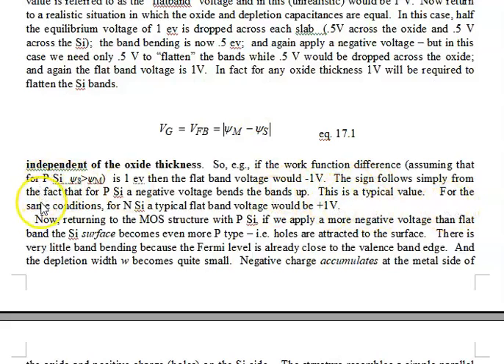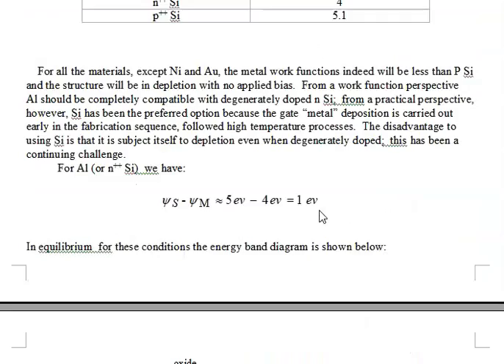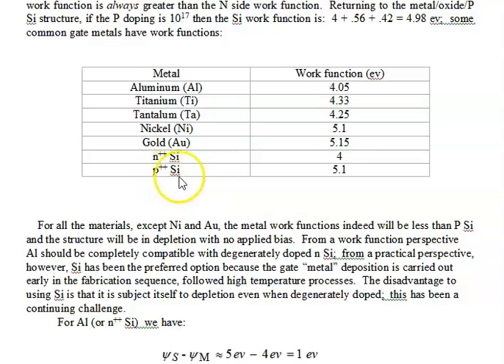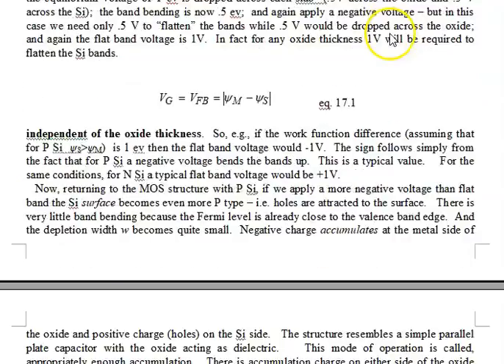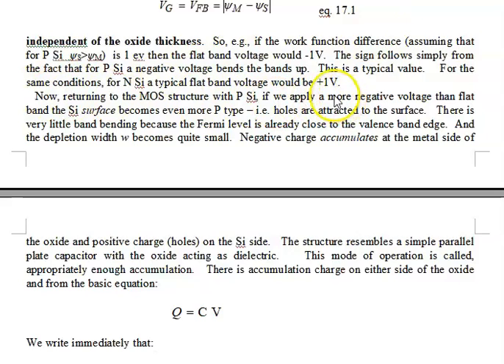Okay, and again, for the same conditions, 10 to the 17th, the work function difference of 1 volt. For N-type silicon, I would apply a positive voltage of 1 volt to flatten out the bands. And what would I have for N-type silicon? Well, there I would generally want to have P++ silicon, because P++ would give me a metal work function of 5.1, and the silicon work function would be about 4, actually about 4.1, 4.2. So that would give me the same exact conditions, and then I just apply a positive voltage. So we don't have to remember that. We just remember forward and reverse. That takes care of everything.